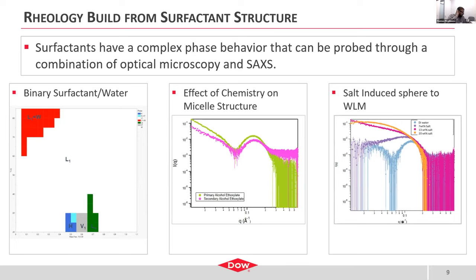And what we assume is that that is a micelle-rich phase. Above 45 weight percent, it forms this hexagonal liquid crystal phase. And then it goes through another phase, and then it forms an alpha lamellar phase. What these are actually is the surfactants reaching a specific concentration in which they undergo further self-assembly from distinct micelles into long-range lyotropic liquid crystals.